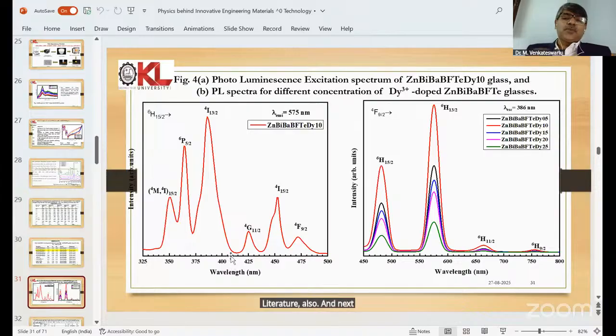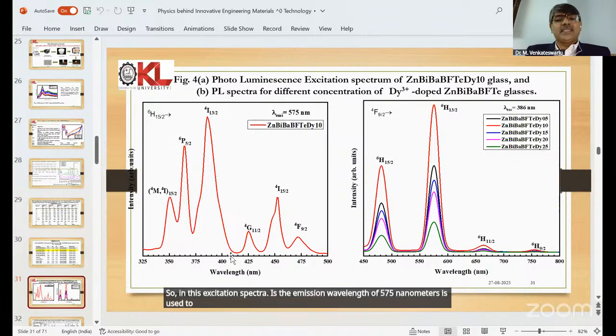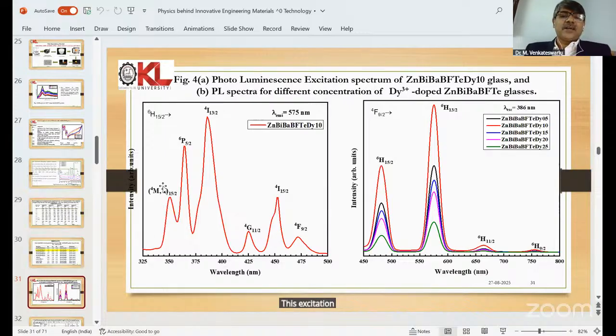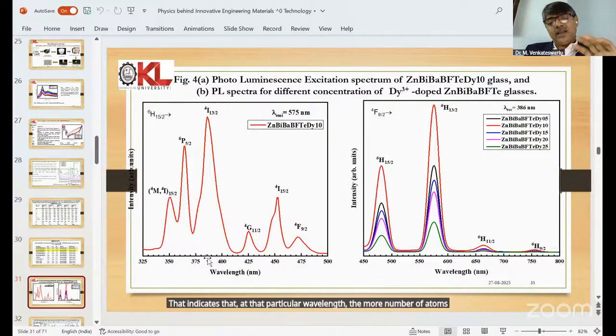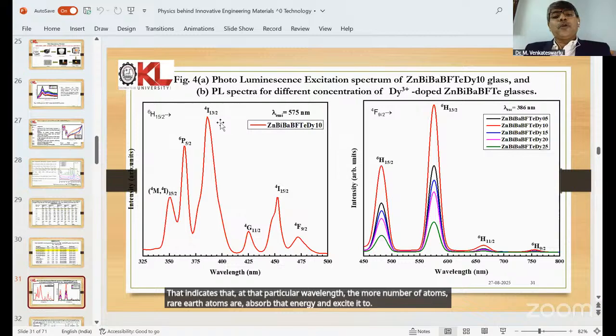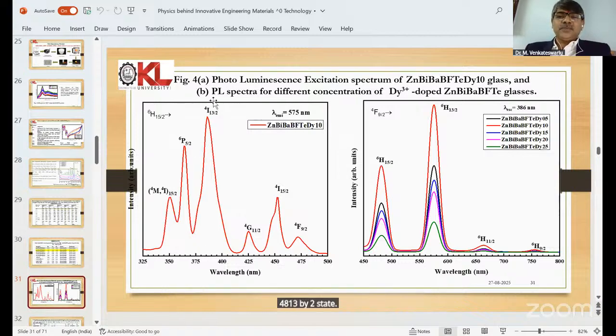And next, once that is over, we considered the excitation spectra. In this, the emission wavelength of 575 nanometers is used to record the excitation spectra. This excitation spectra consists of a total of 8 bands. Out of that, 386 nanometers has the highest intensity. That indicates that at that particular wavelength, the largest number of rare earth atoms absorbed that energy and were excited to the 4I13/2 state. So this wavelength is used to record the emission spectra.